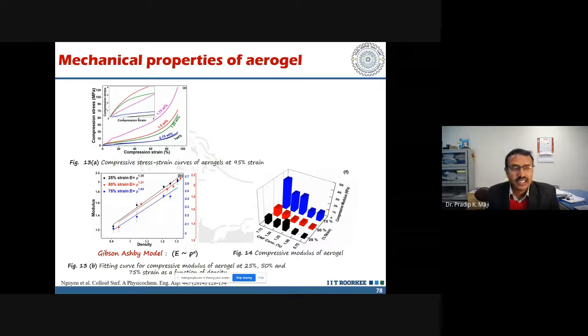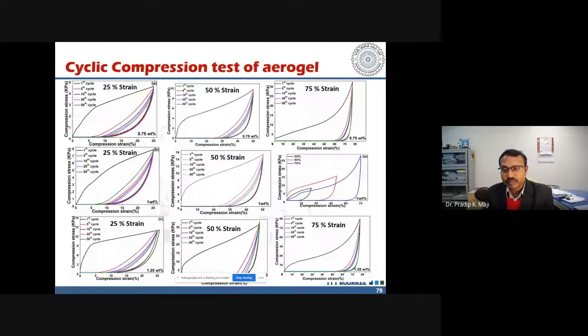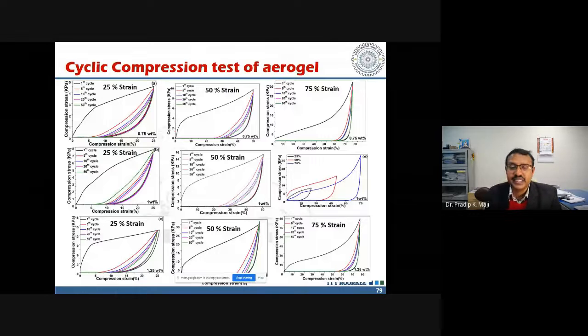This is a mechanical property I have shown you, and here 1.7% by cellulose content is giving better results, but I am interested in the 1.2, 1.5, or 1%. To see cyclic stability, we have checked that also, and it is giving very good results as per the requirement.